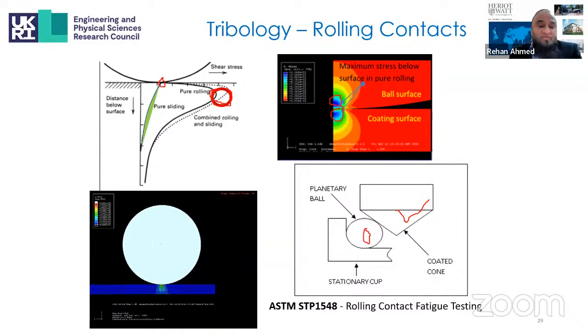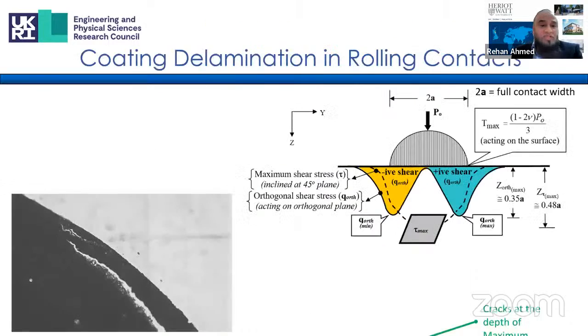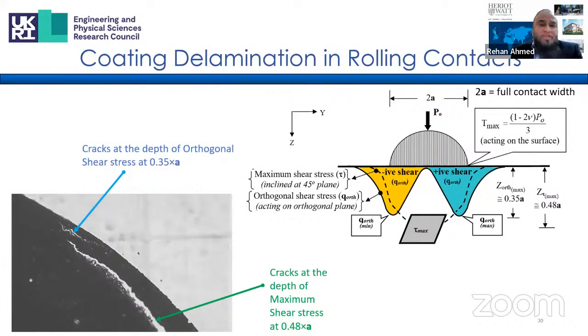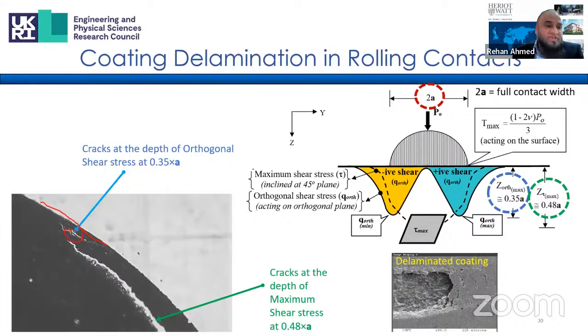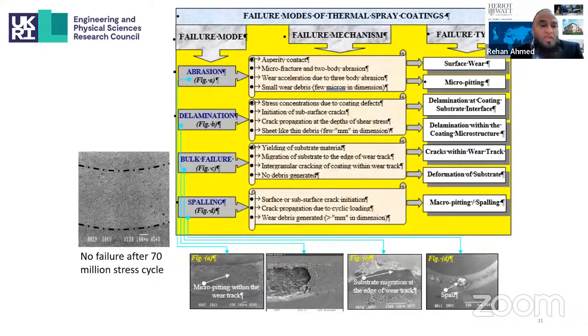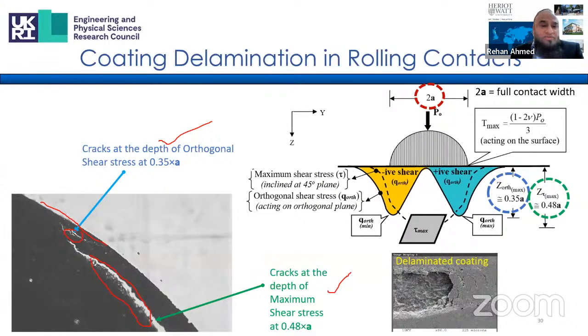The other notable difference is that the friction coefficient in rolling contacts is generally an order of magnitude lower than in sliding contacts. So delamination is a dominant mode of failure in rolling contacts. In this mechanism, the cracks propagate subsurface. This is a cross-section of the coating, so that's the surface. And then you have subsurface cracks, and these cracks appear at 2 different depths of 0.35a, which is the depth of the orthogonal shear stress, and 0.48a, which is the depth of the maximum shear stress. And in the SEM shown over here, you can see what the delaminated coating looks like, where a in this particular case represents the half width of the contact between the 2 bodies.